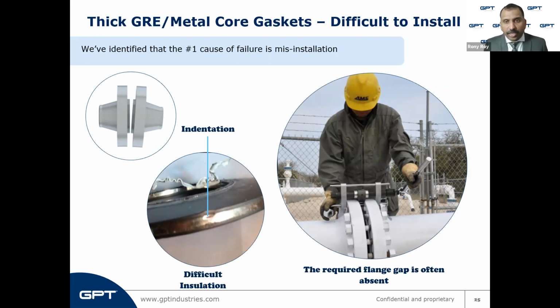In the bottom left image, you can see what happens when the flanges are not spread apart sufficiently and the gaskets could not slide in properly. They are hit by hammers and forced their way inside the flange joint, which can lead to damage of the gasket as well as popping out of the additional seals that are laid into the gasket. We are sometimes told that the gasket was damaged during installation and that the installation was done exactly as the manufacturer has recommended. When we ask to have the gaskets returned, we often see these large indentations in the metallic caused by the installers beating the gasket into the flange. Now, that is not a manufacturer recommendation.